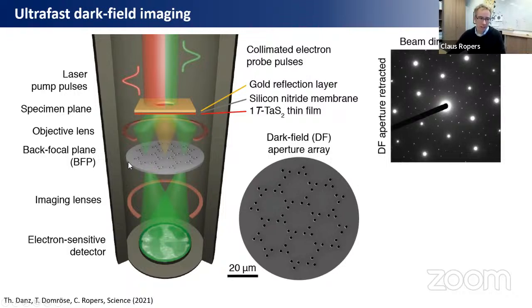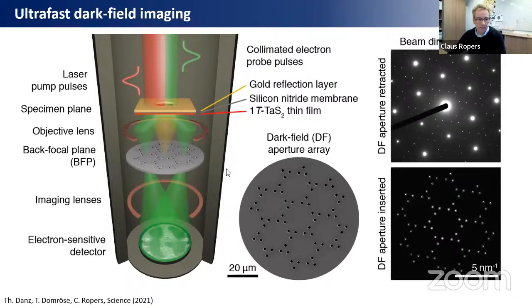So what we can do is place in the back focal plane, so in the far field of this diffraction pattern, a tailored dark field mask which blocks all of these bright diffraction peaks and only transmits the peaks corresponding to the superstructure, arising from diffraction from the lattice distortion. When we place this mask in the back focal plane of the objective lens, and then use the imaging capabilities of the electron microscope to come back to a real space image, we have an analog Fourier filtered image, which gives us information about the spatial distribution of the lattice distortion.